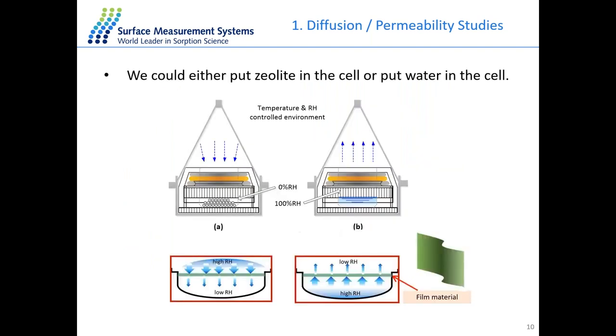There are 2 different configurations we can use with the pen cell. So one, on the left-hand side, we can just put the drying agent inside the cup here, so it will be 0% RH in the cup. And this drying agent will encourage the moisture from outside the cell to be absorbed by the zeolite through the film. Or we can put a droplet of water or other organic vapors in the cup and measure the mass loss when the water molecules are escaping from the film to the outside environment.